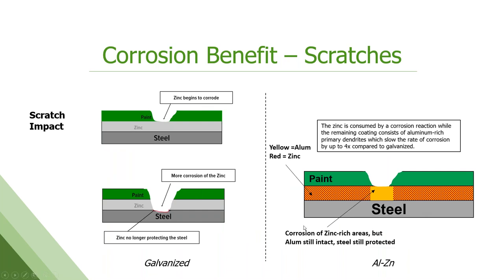This is my little attempt to show what's really going on here. On the left, we have galvanized. Say you've got painted galvanized out in the field and there's a scratch through the paint. Now the zinc layer is showing. That zinc layer is going to corrode and corrode away until eventually there's nothing left and you're down to steel, at which point you're going to get red rust bleeding through to the surface, which looks terrible. It also results in the paint not having anything left to adhere to. So now you've got paint peeling off and bubbling off, which looks unsightly.